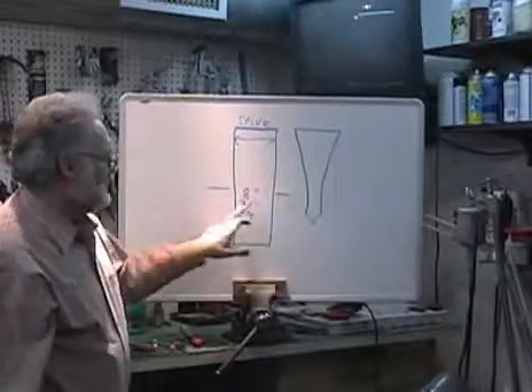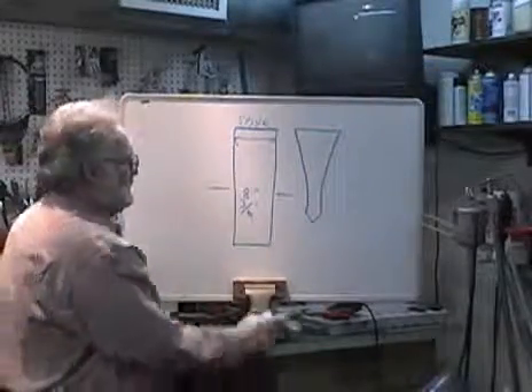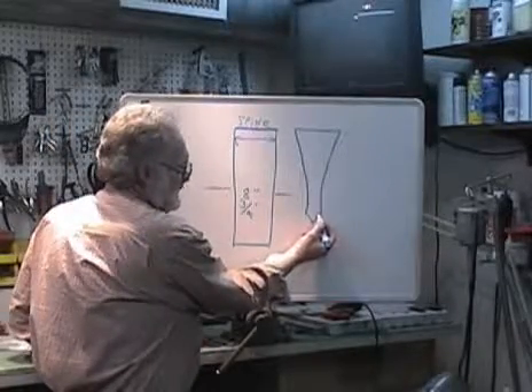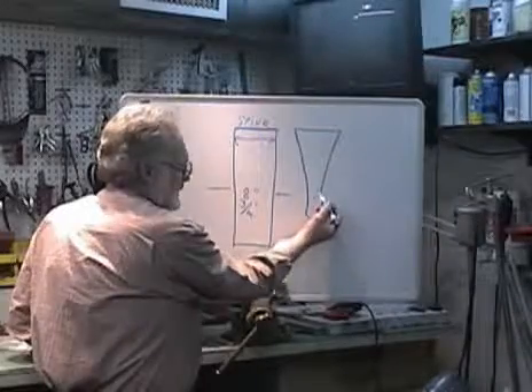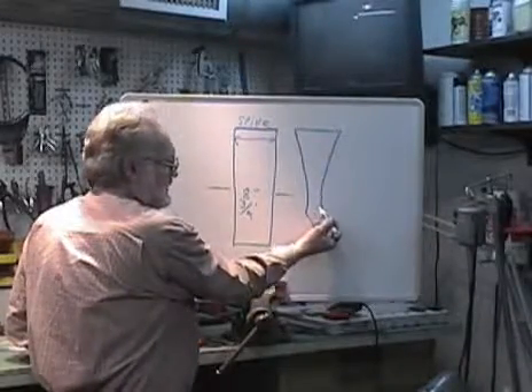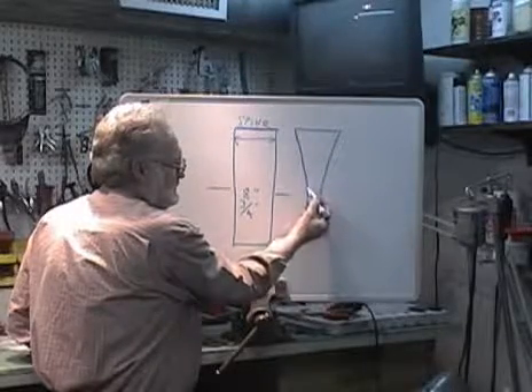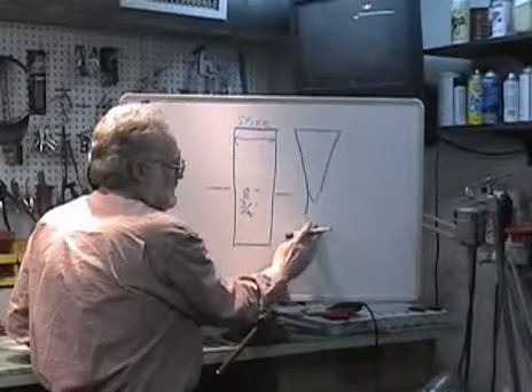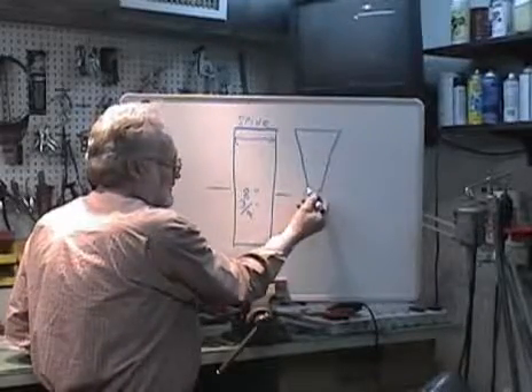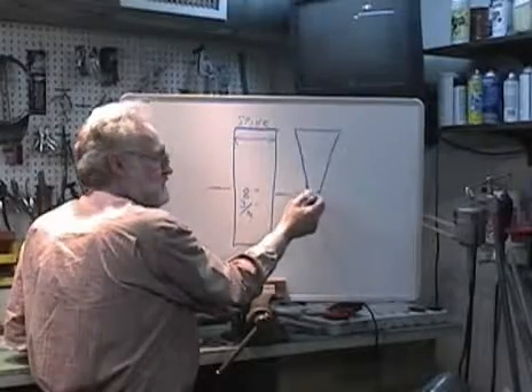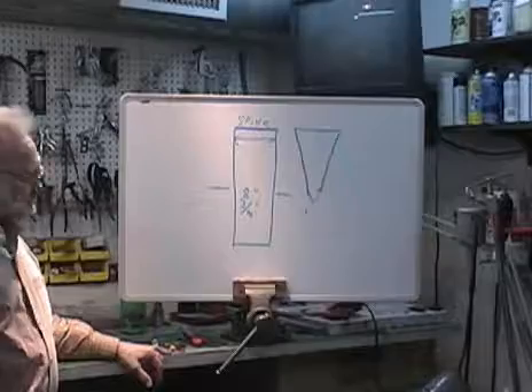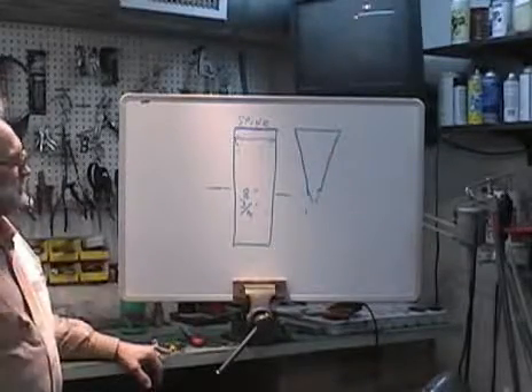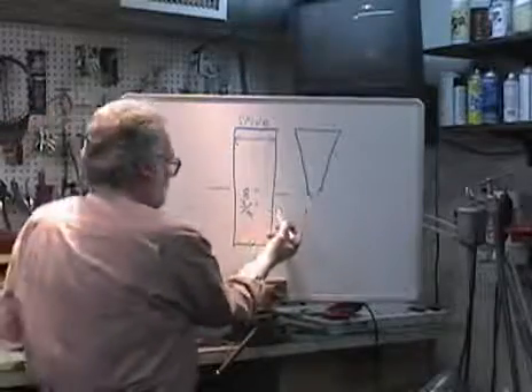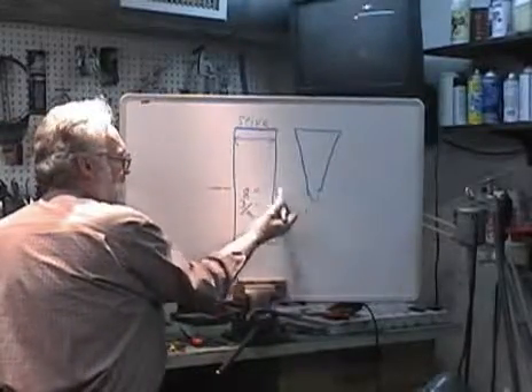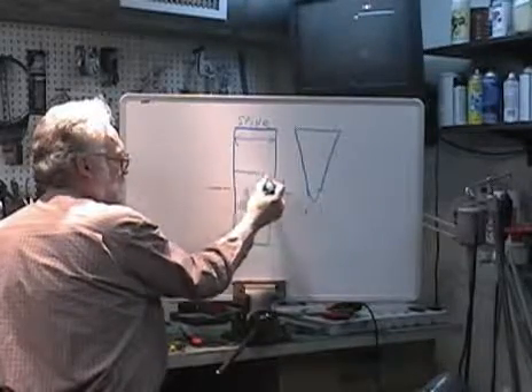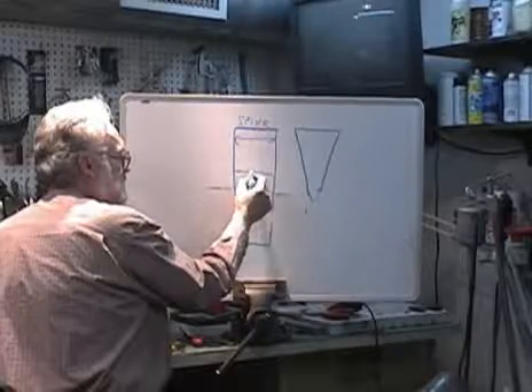Now that's not a lot different than what I showed you a while ago, but what happens is, as you sharpen and continue to work your cutting edge up, you get up into a certain point in the middle of this hourglass, and your blade becomes a lot thinner than it is on the cutting edge, and you have a very weak spot right here that your blade can either bend or it can ripple under the right conditions. So to grind higher, with a 10-inch wheel, you can grind somewhere around, I'm going to say, 1 inch.